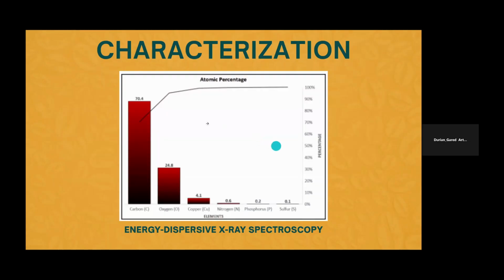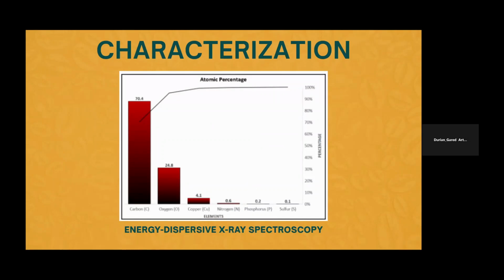Then afterwards, we have here our EDX analysis of the sample, which indicates that it primarily consists of carbon, which accounts for 70.4%, and oxygen, which accounts for 24.8%, and other trace amounts of copper, nitrogen, and phosphorus. These elemental proportions align with the expected composition of graphene oxide quantum dots, which are mainly composed of carbon atoms arranged in a graphitic structure and functionalized with oxygen-containing groups.